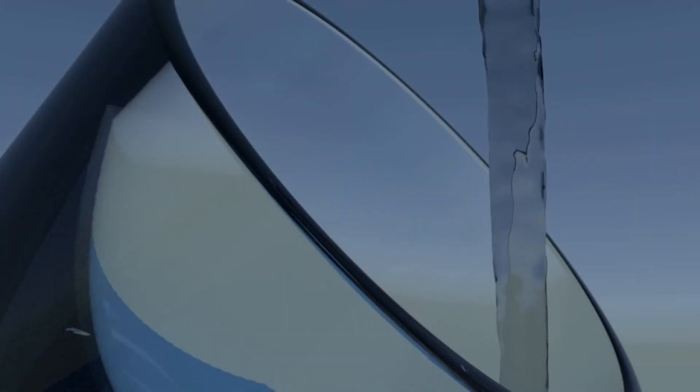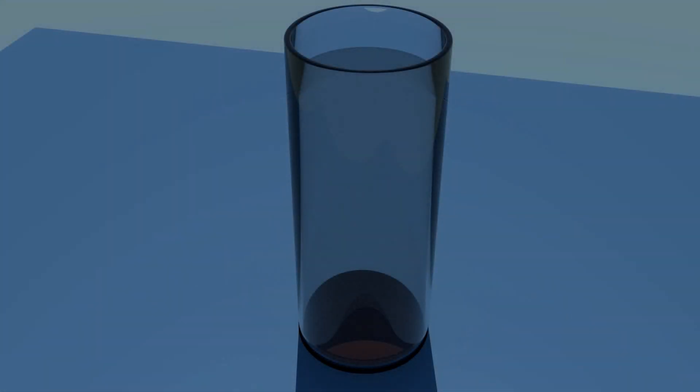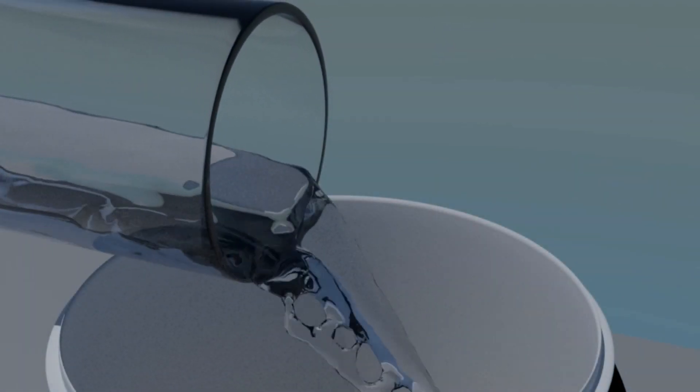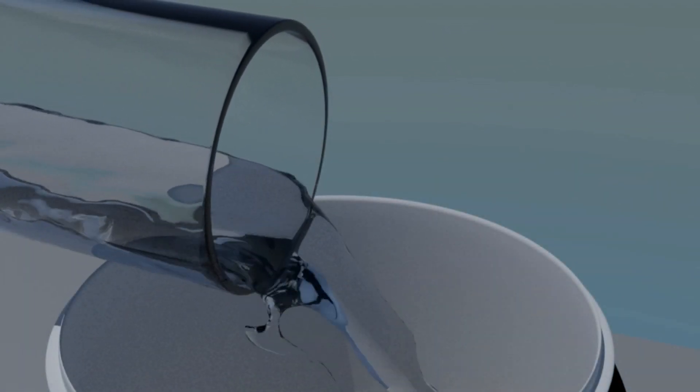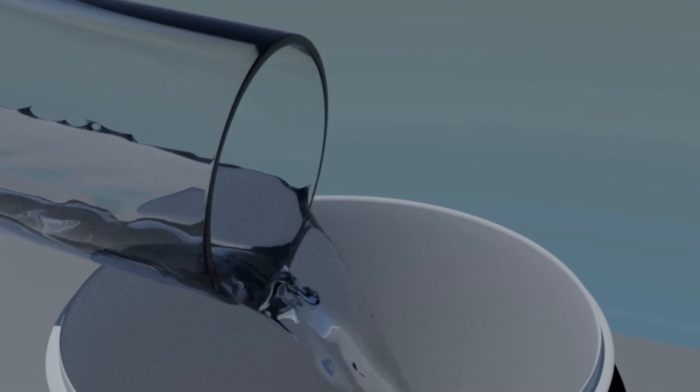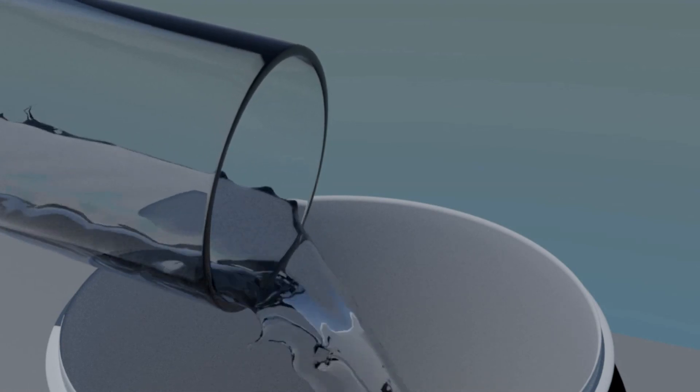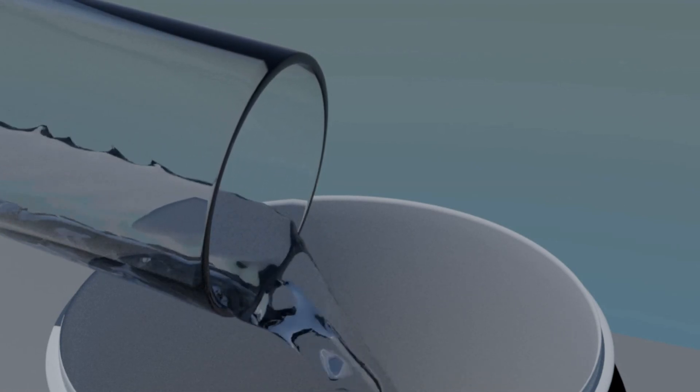Add water. You can use either tap water or bottled water. Fill the chamber within about 2 to 3 inches from the top. That's about 2 liters of water. Then give the particles a few minutes to settle to the bottom of the chamber. When the particles have settled, decant the solution, taking care that all the particles remain in the chamber and are not inadvertently poured off with the water.